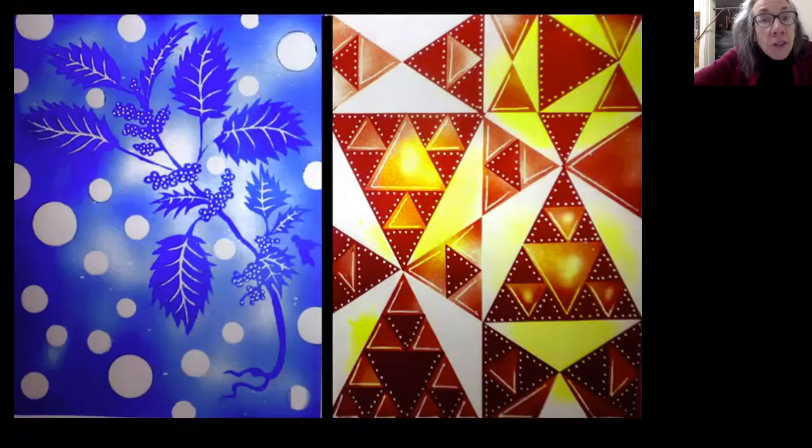First off, you can engrave any glass surface, but it is much easier to engrave a sandblasted surface. Sometimes the frost is quite thick and it makes sense to thin it out a bit. Also, you can mark the sandblasted surface with a permanent marker such as a Sharpie, and it won't wipe off when it gets wet. Like the unsandblasted surface of glass, it will wipe right off of that. So it's much more permanent.